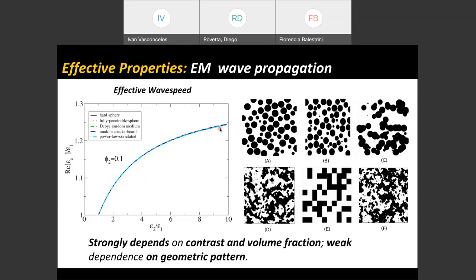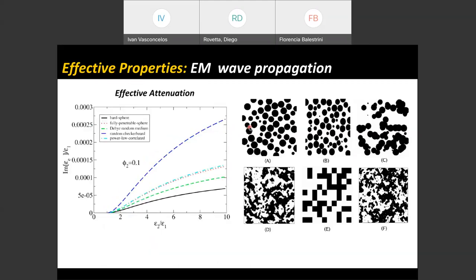But remember I said that the theory we used uses the actual wave equation. That means that at certain frequencies, the effect of Rayleigh scattering occurs. So Rayleigh scattering is a subwavelength scattering effect that produces attenuation. It's the same effect that makes the sky blue, for example, right? So let's look at effective attenuation here. Now, remember, neither black nor white is attenuative, but the effective properties are because we use a wave equation effective property calculation. Now you can see effective attenuation as a function of contrast for a fixed volume fraction.